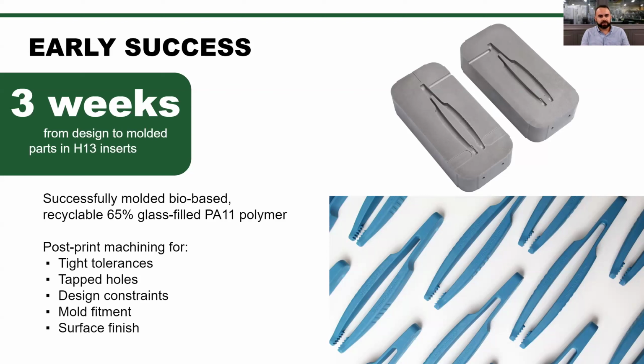So within 3 weeks, we reverse engineered, we designed the cavities, we printed, and then we had to do some post-processing, but we did not touch any of the molding geometry. Everything was as-printed, mold and geometry wise. The only thing that we had to do was square up the block, tap your water lines, EDM burn your subgate, and then wire your ejector pin holes. With that, we had very minimal witness lines or anything. Everything was aligned well, and we were molding 1,000 parts for them within 3 weeks. We just threw the cavities into our 0809 mud frame and had no issues moving forward.